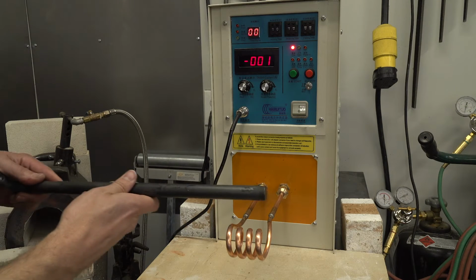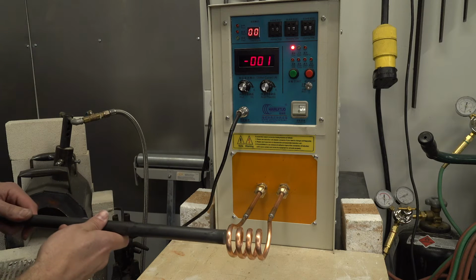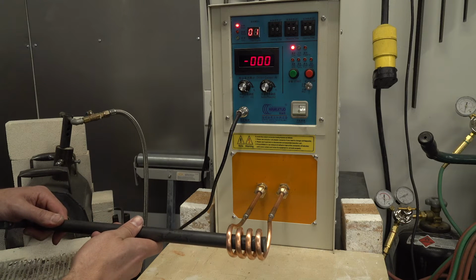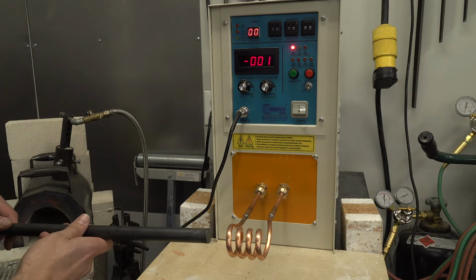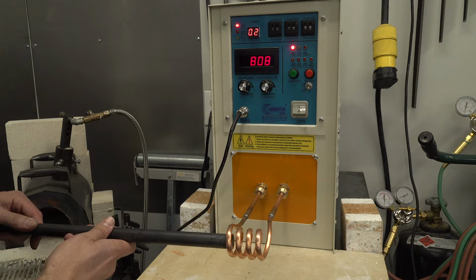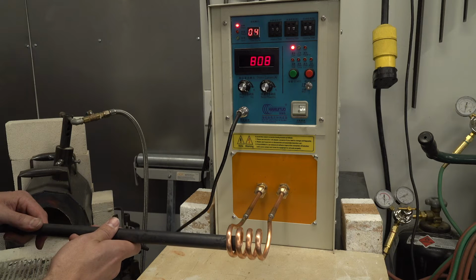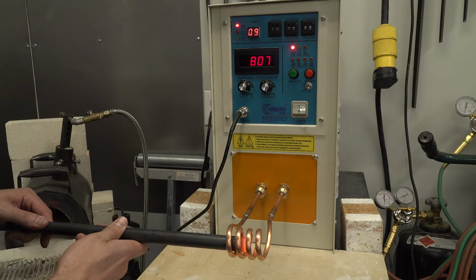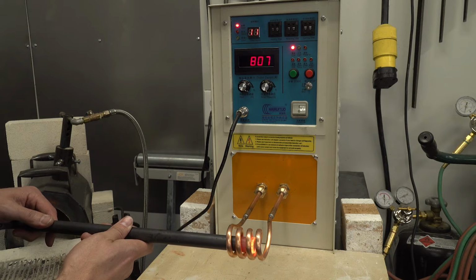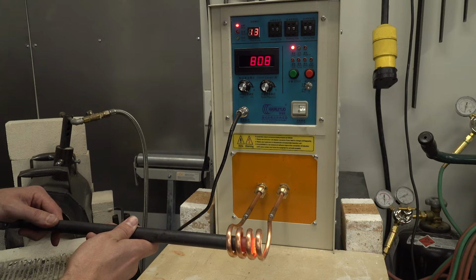If the material is too big for the coil being used, you'll notice that when you start to heat it, the amperage will drop down to 0 and the machine will make a clicking noise instead of starting. This is because the inductance is too high. However, if you slowly insert the material while the machine is running, you'll notice that it'll heat the end of the material and then eventually the whole area inside of the coil. This is because as the material heats up, its inductance decreases and the machine can stay in range.